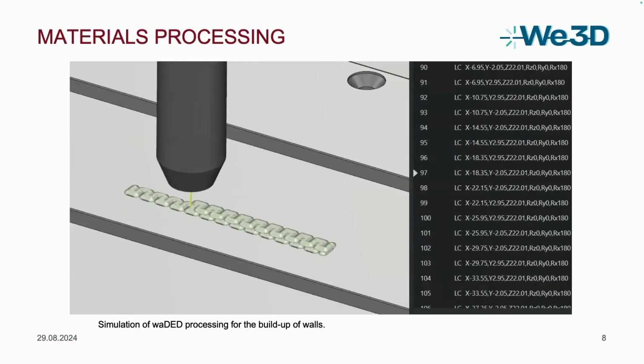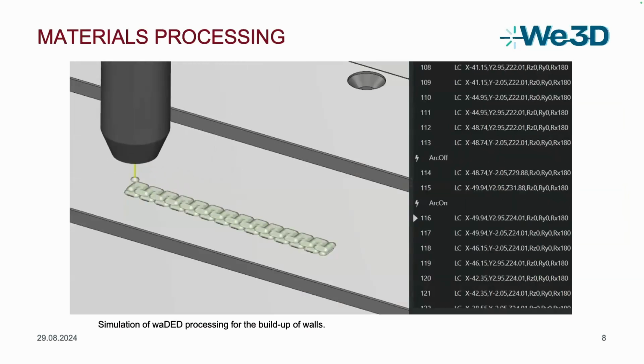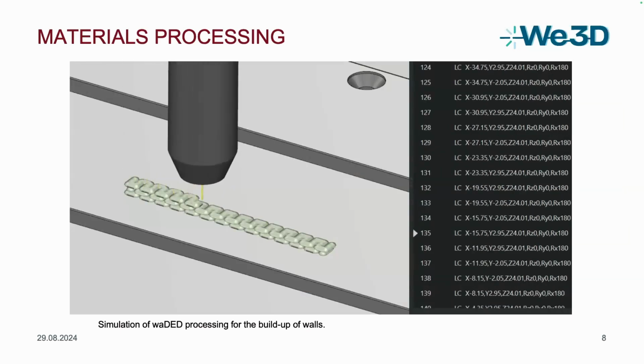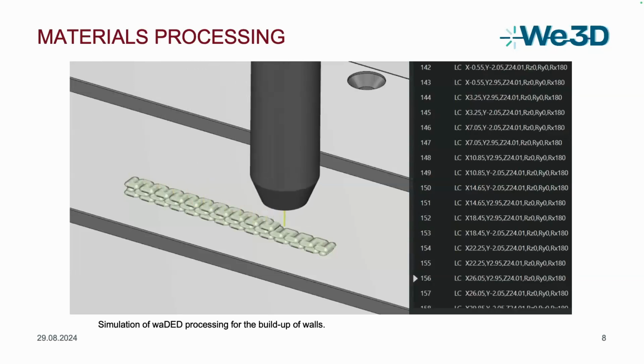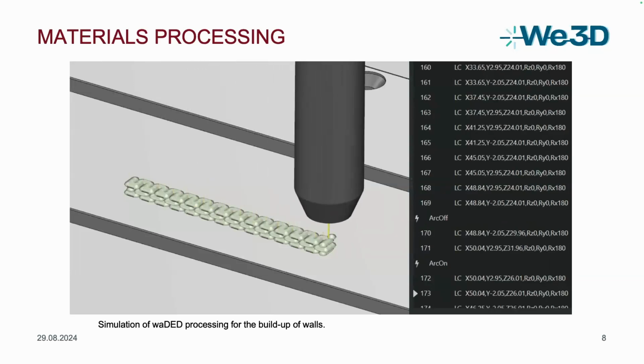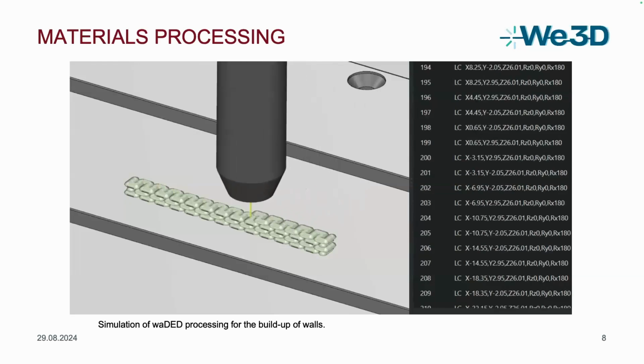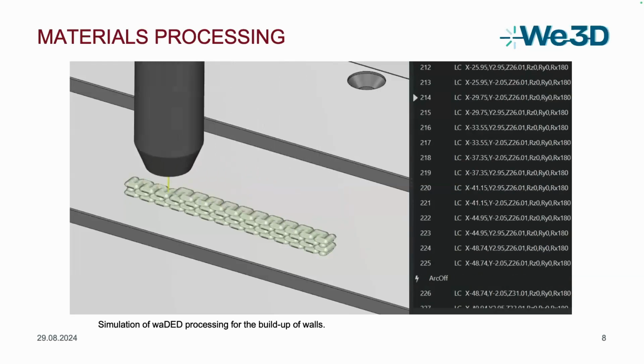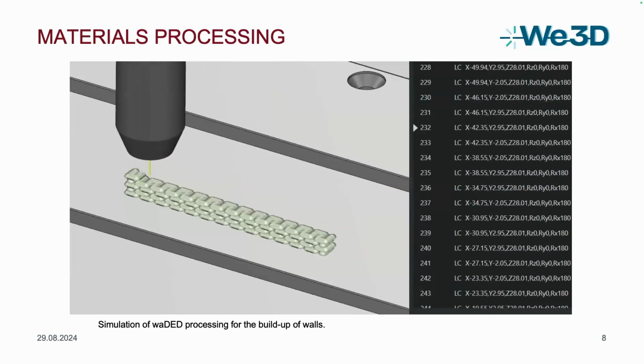Here we can see the build-up strategy for the wire arc DED wall. Basically, we have an alternation of the process direction with every layer, and also we did apply a weaving movement to get broader walls for the milling process afterwards.